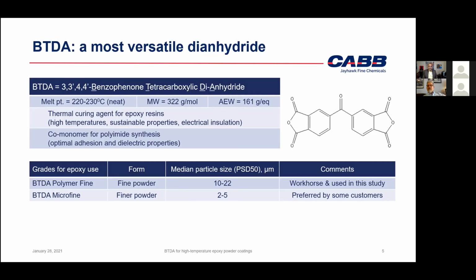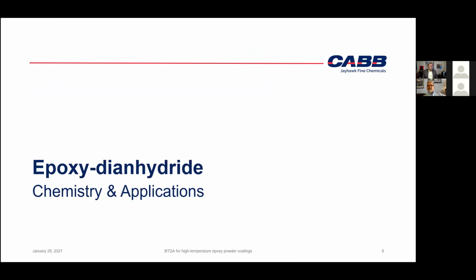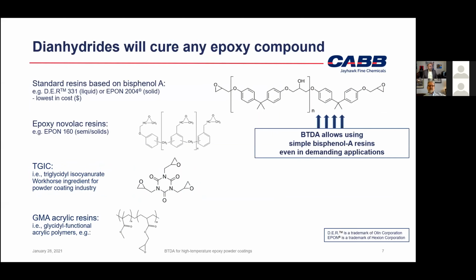Perfect. Thanks, good point. Let's take a quick look at the chemistry of these kinds of systems. So a dianhydride like BTDA will cure any epoxy compound. Obviously, it's just looking for the epoxide functional group. Now, many other curing agents can give you high performance, but for them to give you high performance and high cross-link densities, they actually need to have an epoxy resin of high functionality to begin with. Epoxy Novolac resin would be one example, where some curing agents will give you high performance using the high functionality